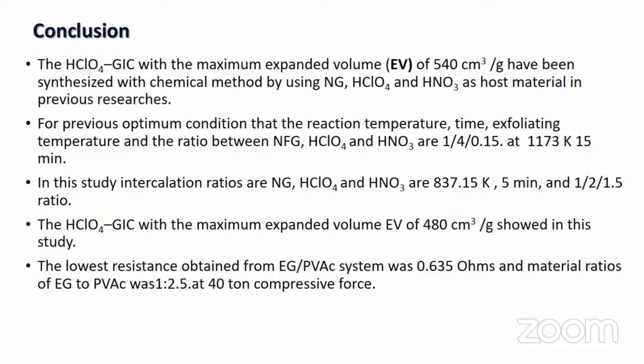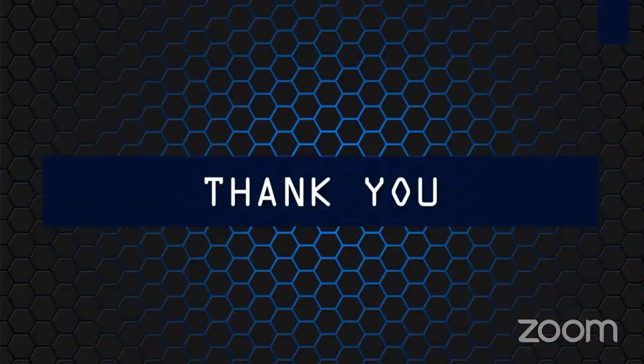This also gives the maximum expanded volume of the graphite, 480 cubic centimeters per gram, in this study. The lowest resistance obtained was 0.635 ohms, and the material ratio of EG to PVAC was 1 to 2.5. The pressure applied for compression is 40 tons. Thank you.